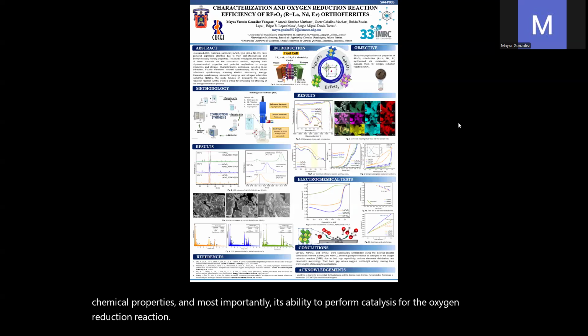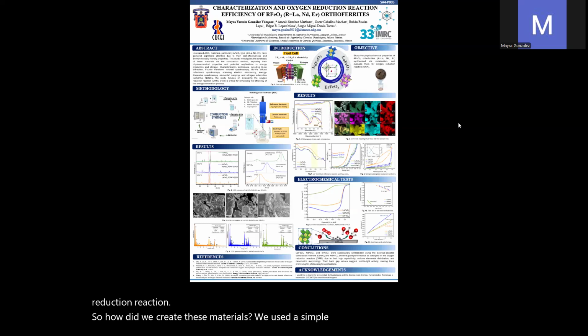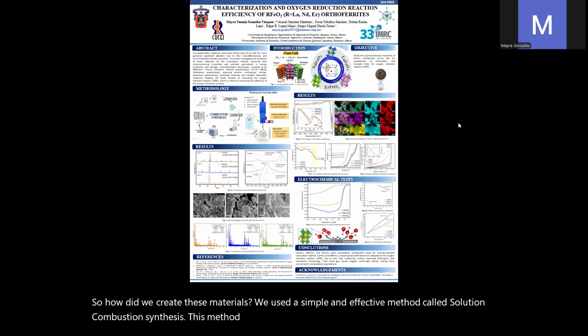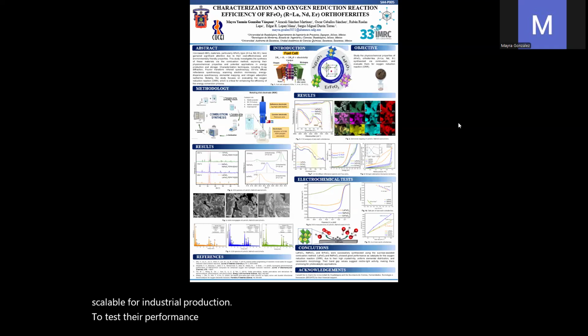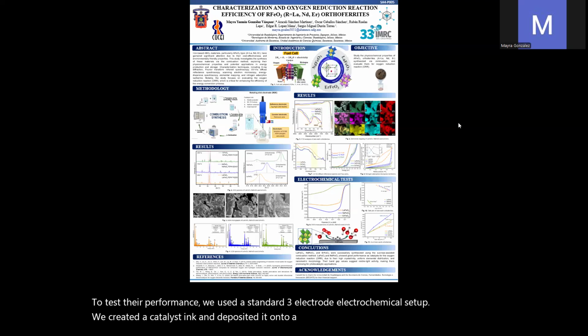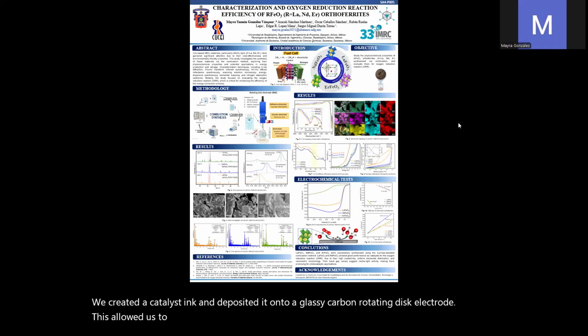So, how did we create these materials? We used a simple and effective method called solution combustion synthesis. This method is excellent because it is fast, energy efficient, and easily scalable for industrial production. To test their performance, we used a standard 3-electrode electrochemical setup. We created a catalyst ink and deposited it onto a glassy carbon rotating disc electrode. This allowed us to measure the material's activity for the ORR in an alkaline solution.